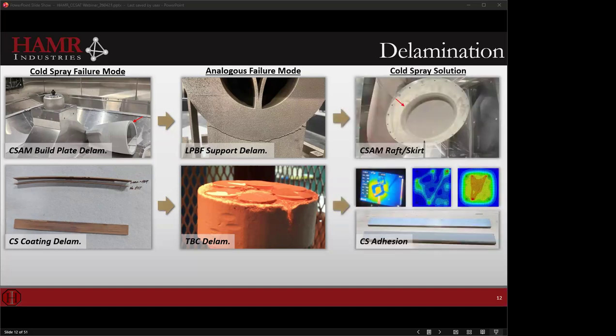It's not new, so we can borrow some of those solutions. In the case of the top, we can look at something like a raft or a skirt, borrowing from what we do on our FDM benchtop printers, and it works. It's certainly a viable approach, and we can change our DFAM, reduce our stress risers, look at our contact area, contact patches, and use that to ensure that we have adhesion.